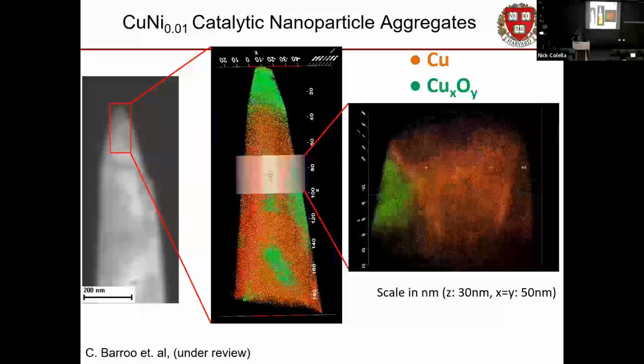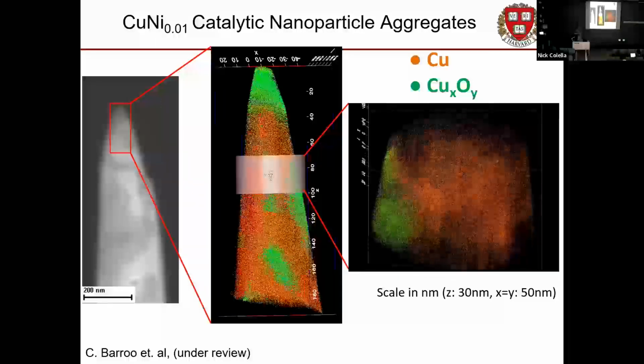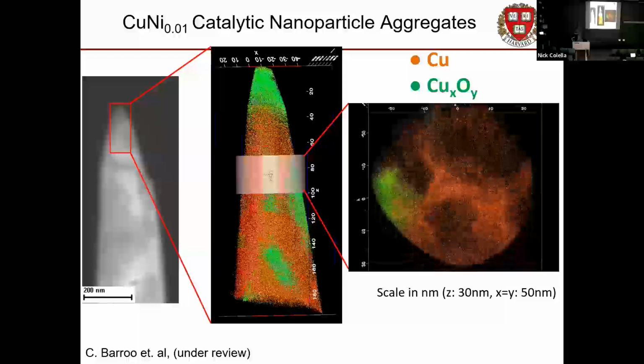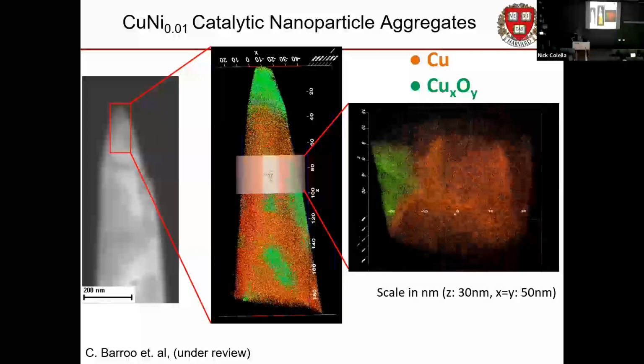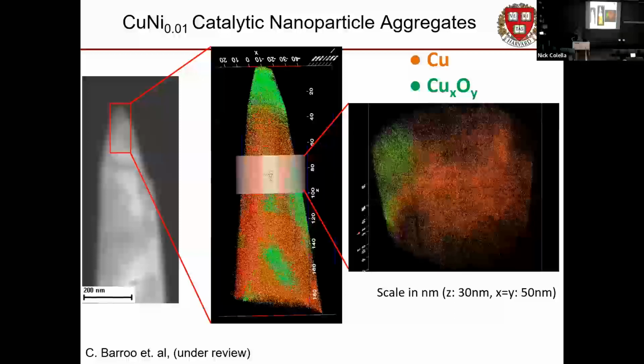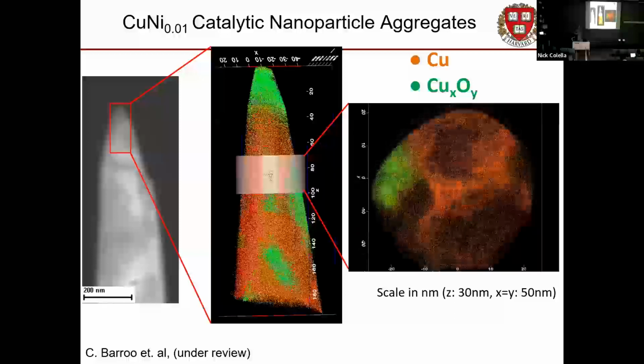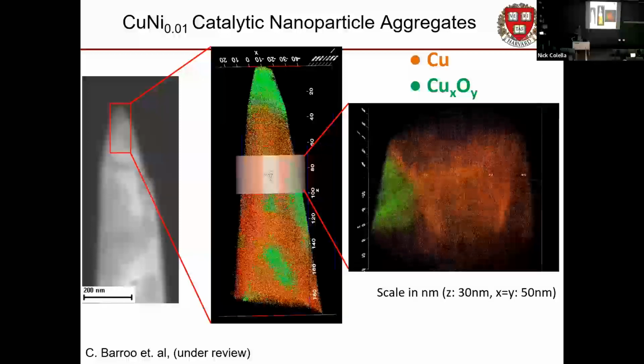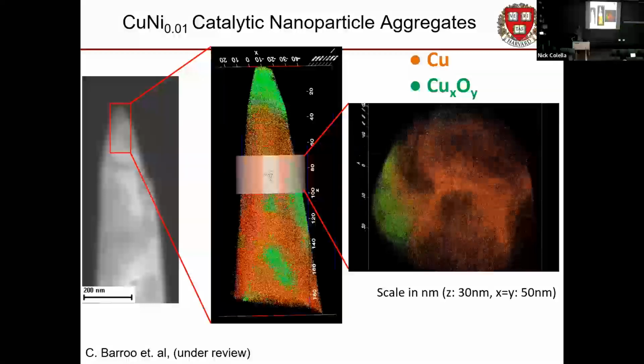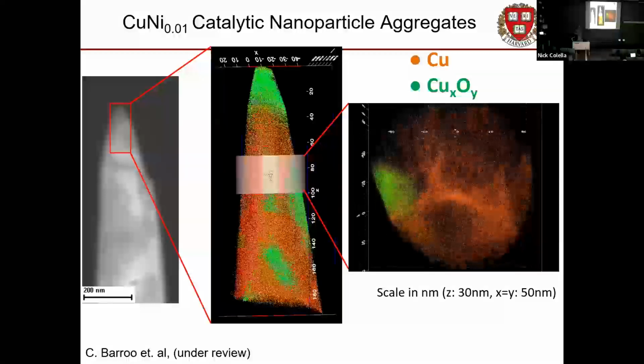Turns out that when they made these, they made copper nanoparticles and an occasional nickel nanoparticle. And then when they did composition analysis, they dissolved them all in acid and sent them off for mass spec that way, and it came out at 1% nickel, but it's 1 nickel nanoparticle for every 100 copper. There's no actual nickel atoms in these copper particles. So now we know that.